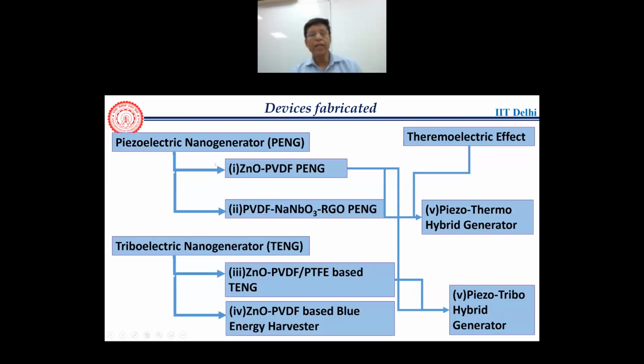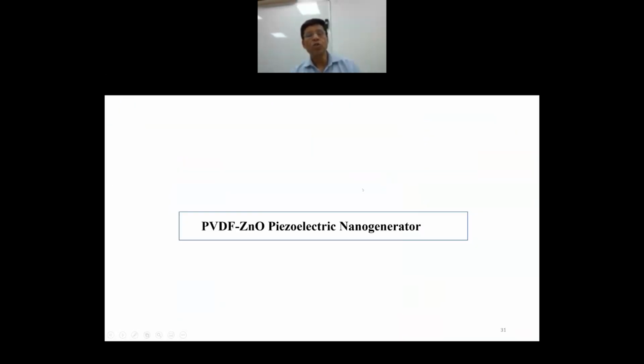Okay, so another thing we did was piezoelectric force microscopy study to find out more detail. This piezoelectric force microscopy is based on applying some kind of pressure, and then we can find out the D33 parameter. This measurement of the D33 parameter is very useful to find out how much the piezo property has enhanced once we have this nanocomposite film. And this is the tool we have used. This is basically an atomic force microscope, in which this piezo tip is used, and this is used to find out the PE loop at a localized point.